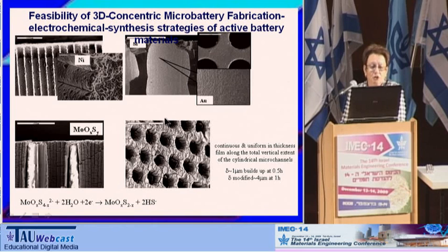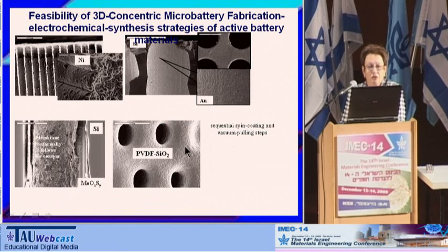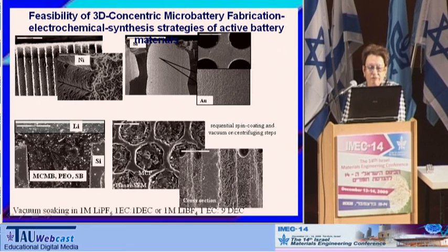cathode. From the AFM images at the bottom, one can see that the layer inside the microchannels is continuous, and the morphology of the deposits is very similar inside the layer and on the planar surface. The evidence of the formation of the hybrid polymer electrolyte membrane, which conformally follows all the previous battery layers, can be seen in the following AFM images.